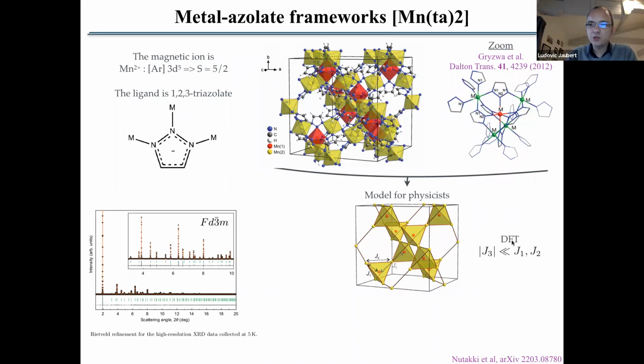And ab initio DFT calculation tells us that J1 and J2 are of the same order of magnitude, while J3 is much smaller because J3 does not have the nice nitrogen connection between them. Okay. And so you can see that J1 and J2 are the same order because for J1 you go through N2 and N1, while for J2 you go through N1, N2, and N1. So it's just adding one more nitrogen difference between the J1 and J2 coupling. So that's why they are of the same order of magnitude.